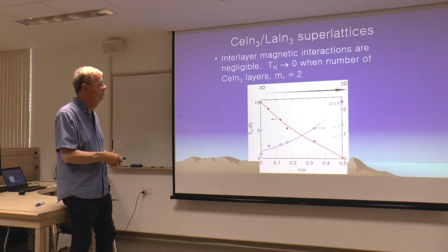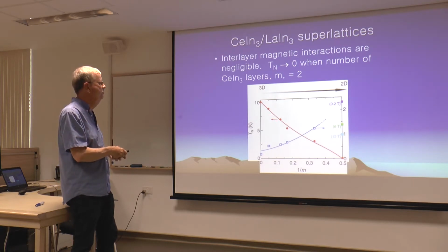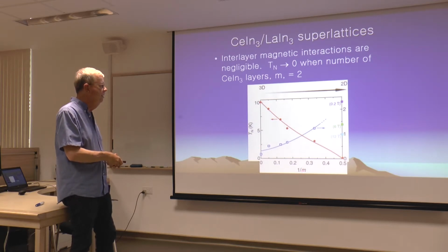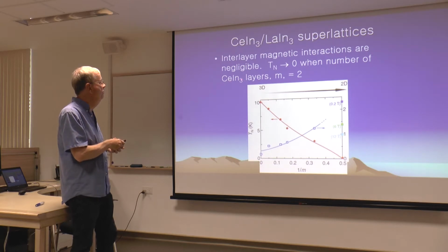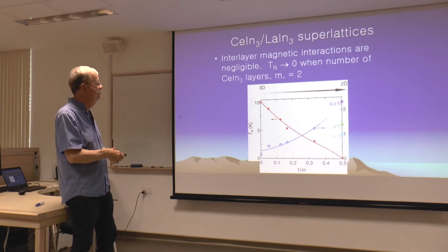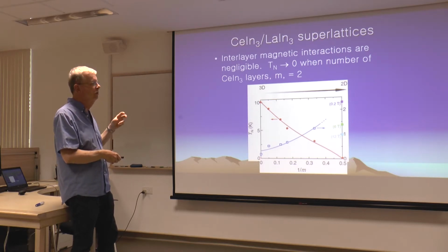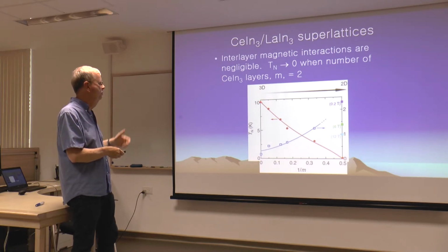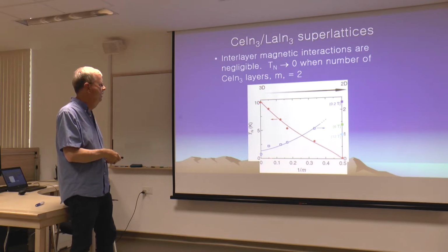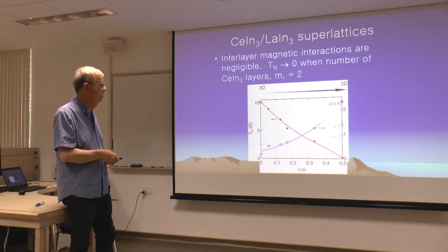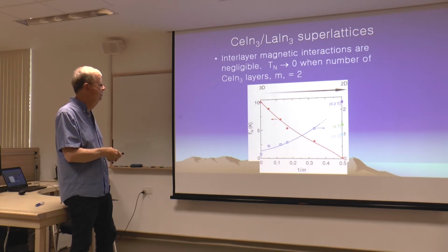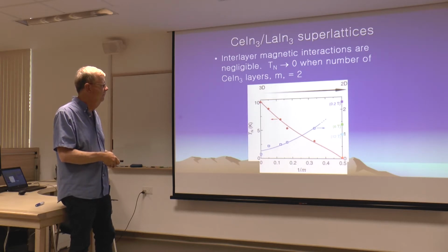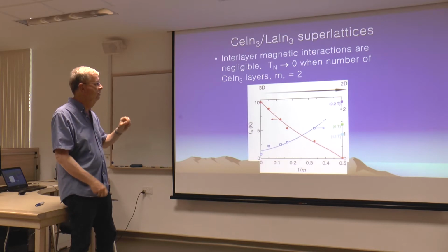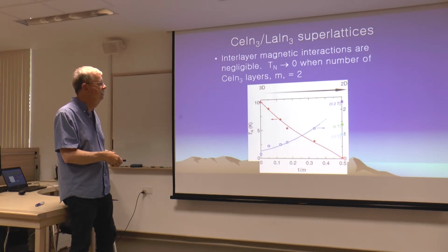First of all, I'm hiding this from you. I have not labeled this axis yet. Don't worry about this axis. We're not there yet. We're over here on this axis, looking at the red points. This is the Néel temperature. M is the number of cerium indium-3 layers in between the lanthanum indium-3 layers. So if I go to a big number, so I've got bulk cerium indium-3, then of course the antiferromagnetic transition is where we think it is. It's up around 10.2 Kelvin. As I make the number of layers more like 3, you can see that the Néel temperature has dropped down here to a much lower temperature. And if I make the number of layers only 2, I get rid of correlations that are leading to the long-range antiferromagnetism, and my T-Néel drops to 0.